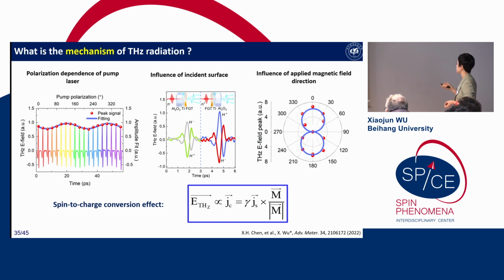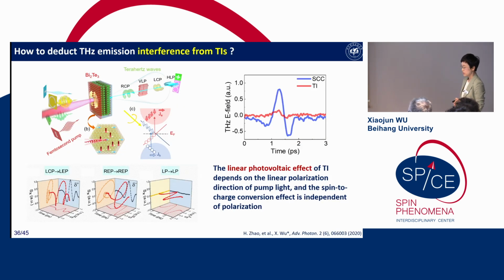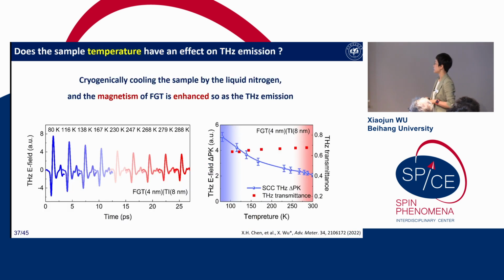And then when we rotate the magnetic field, we get this distribution with very perfect symmetry. So with this kind of measurement, we verify it is a spin-to-charge conversion effect. To extract the spin-to-charge conversion component, we directly use linearly polarized illumination on bismuth telluride, and we can extract the SCC component and get rid of the component from the topological insulator. And at room temperature, we get terahertz.